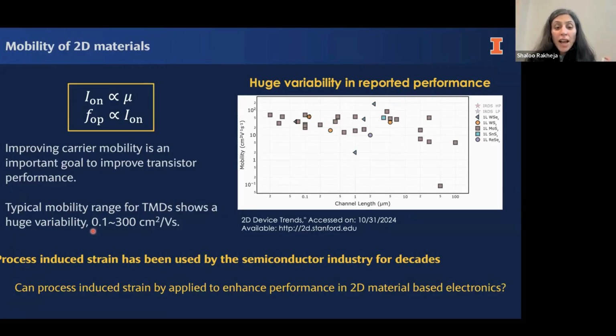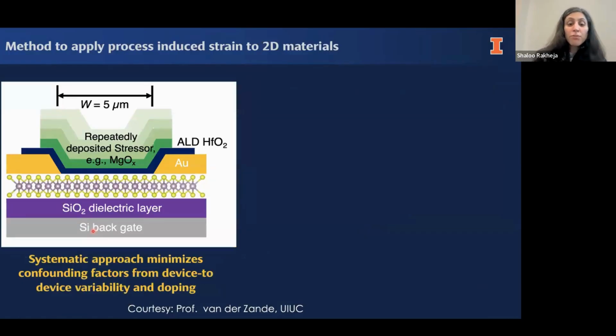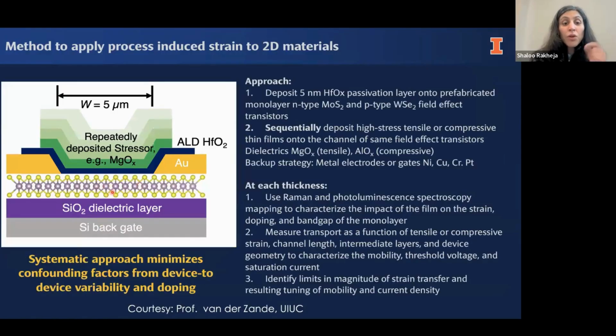So the real question is, can we apply process-induced strain to these 2D materials, and can we get a more tightly controlled performance, better performance than this random map that I've shown over here? My colleagues at UIUC, Professor Van der Zande's group, have developed a method to apply process-induced strain in a very gradual and systematic manner. So as you see over here, this is a 2D material. What they do on this 2D material is they deposit a stressor layer. A stressor layer is a material like MgO or aluminum oxide. MgO typically applies tensile strain. Tensile strain is where you're really stretching the atoms. And if you think of aluminum oxide, that's compressive, so it brings the atoms closer to each other.